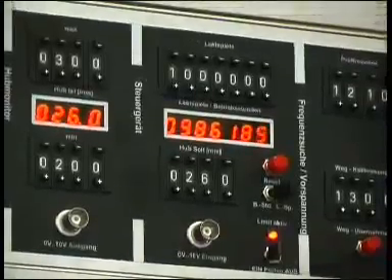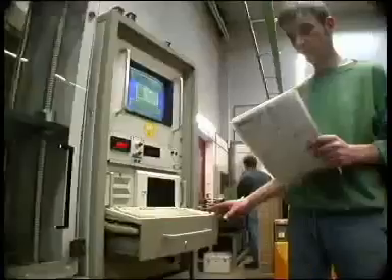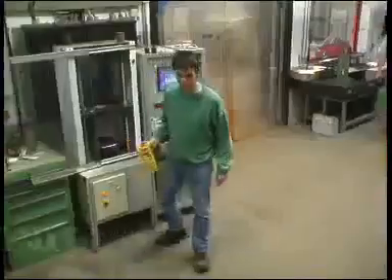At the end, there is the final inspection: a final check of the dimensions, the spring rate, and other specifications. In fatigue tests, suspension springs must, for example, withstand at least 500,000 times the full application of load and subsequent relief. Other products that we manufacture are even vibrated up to 3 million cycles — for example, springs for fuel injection pumps — and this is a growing trend.